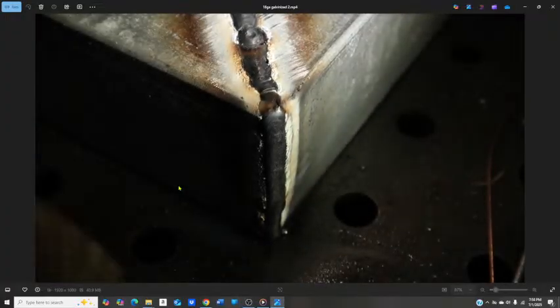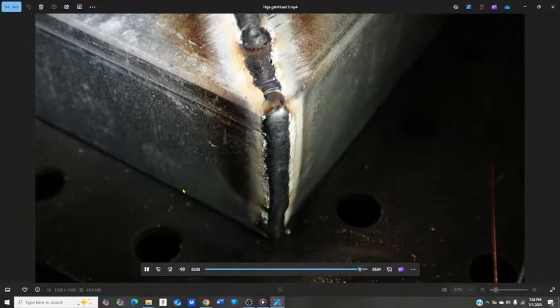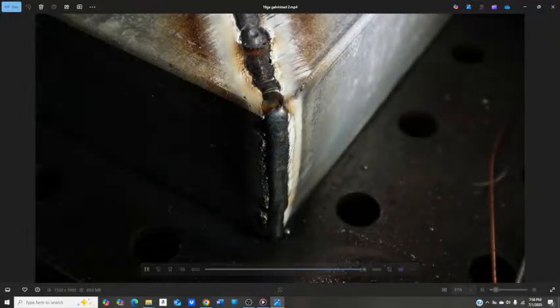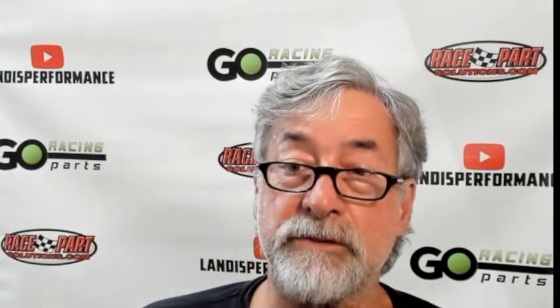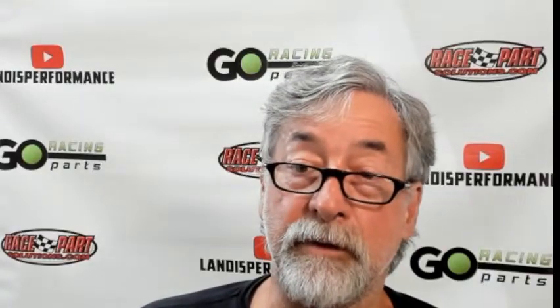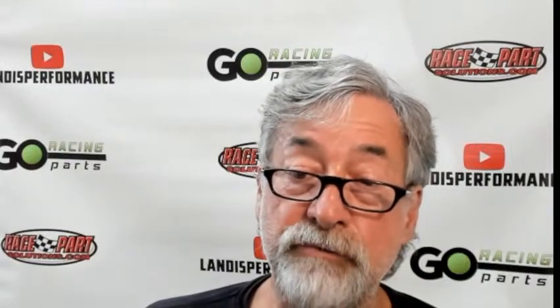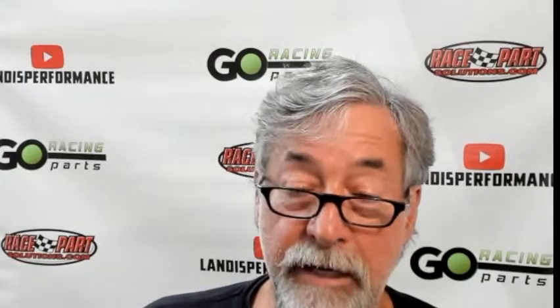Now at the end of that, now on that, again, because it's galvanized, you won't see the stacking of dimes as well, because the galvanized is in the weld. The gas purge over top of the weld can't keep the galvanized out because it's in the metal. But I hope you could see that puddle when I was going down. You could see it kind of yellowish, and it was kind of following the torch as I'm going down. Now, as I got to the bottom, I started getting the torch too far away from the metal, and it started getting spattery, and that's because the gas plume wasn't covering the weld anymore, and it was getting contaminants in there.